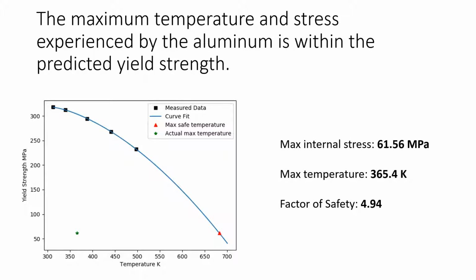Estimating that the maximum internal stress experienced by the aluminum casing to be 61.56 megapascals and a maximum operating temperature of 365.4 Kelvin, the yield strength is about 5 times larger than the expected stress. The temperature may seem low, but the phenolic liner is an excellent insulator, making this a reasonable maximum temperature. Additionally, if the motor got near the maximum safe temperature of 682 Kelvin, residual stress and tempering would occur with repeated use, making the motor unstable. Remaining well within the limit increases the lifespan of the motor casing.